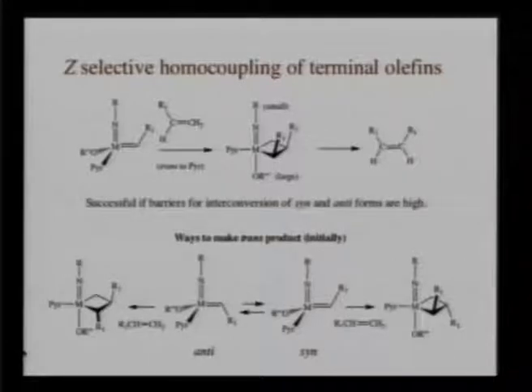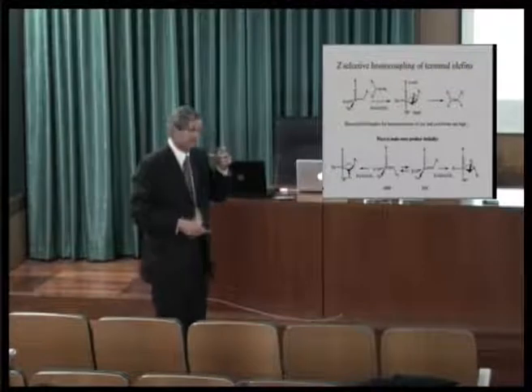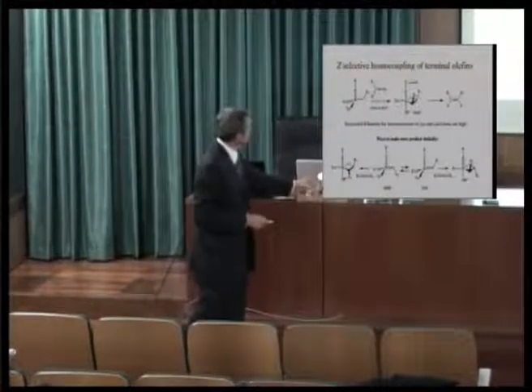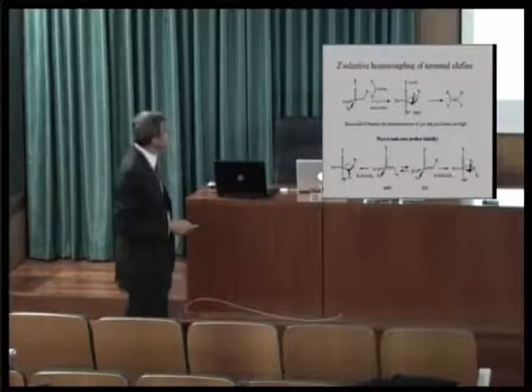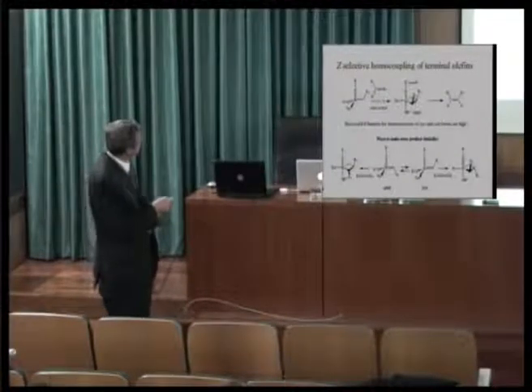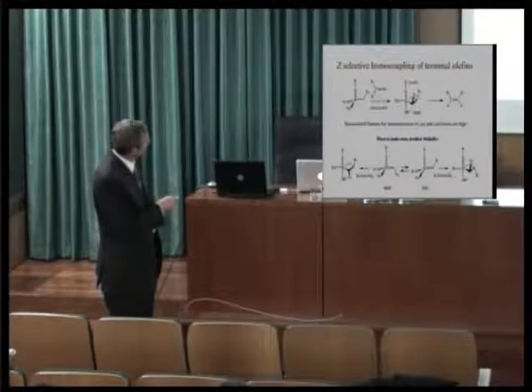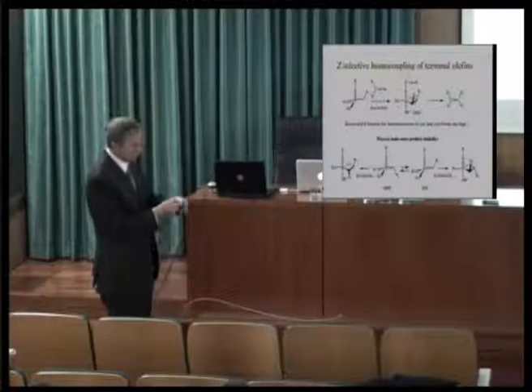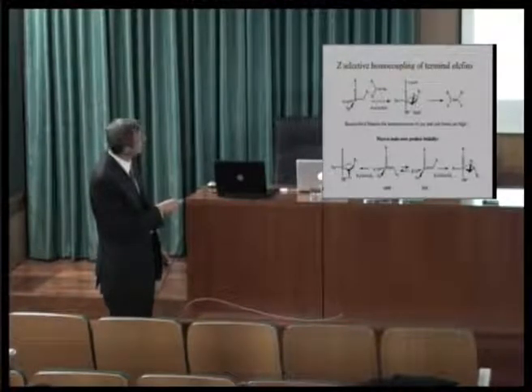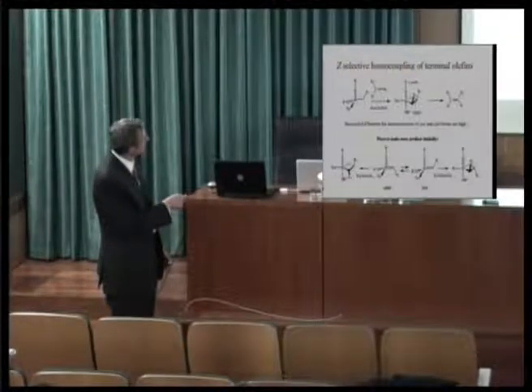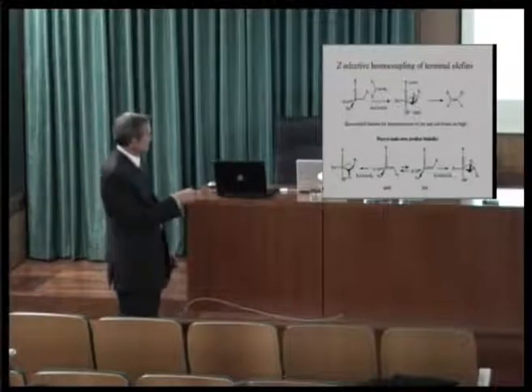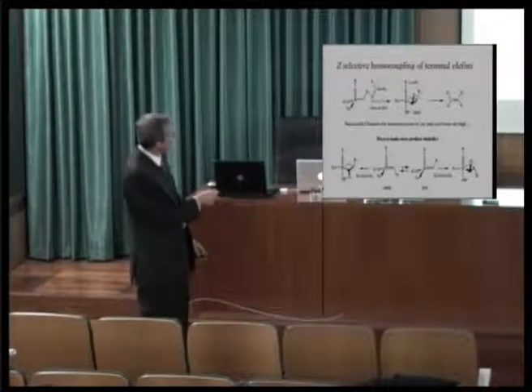So is it possible to do Z-selective couplings? This is the grand prize of metathesis, and the answer is yes, it is, using these types of compounds I just mentioned, for the reasons that I just mentioned. A substituted alkylidene will react with a terminal olefin to give one of two intermediate metallocycles. This is the one that will give rise to product, and that product has to be Z, and the methylene species will react with this olefin to give ethylene and go back to this species. So this is possible just by restricting, as I said, these R groups to point up.